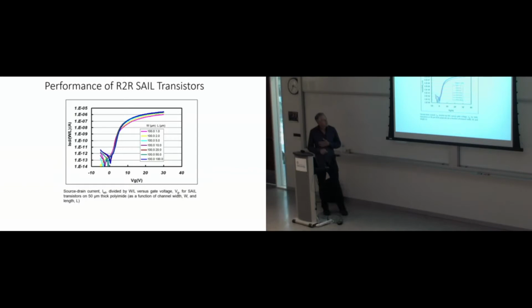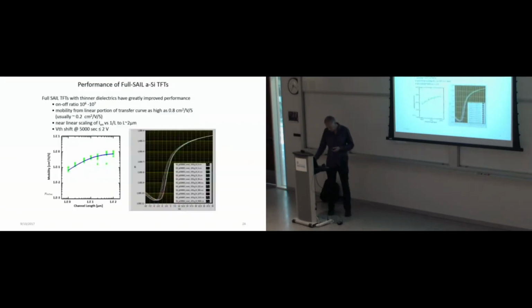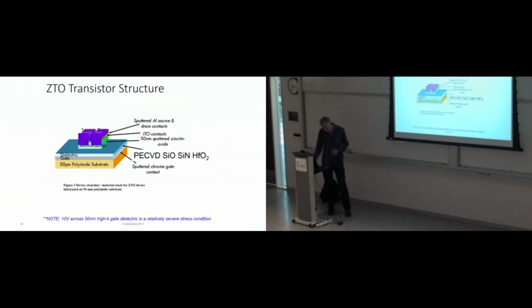But anyway, these are quite good transistors, particularly at the 5 micron. Remember, because you're dividing by W over L, which is 20, we're actually getting 20 microamps out, which is pretty good for amorphous. It's partly because you have a small device. And remember, we're doing it over 13 inches. And you can get decent mobilities of almost 1 and very low off currents in general.